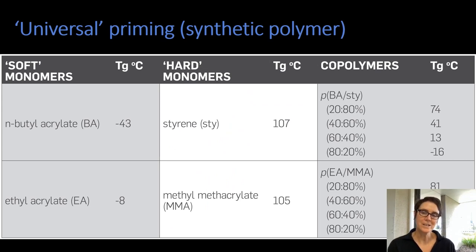Although characterization of the percentage combinations of monomers was beyond the scope of this study, it's useful to note that different monomers are combined to achieve desired acrylic product characteristics, such as softness and hardness. You can see here that combining a higher percentage styrene to butyl acrylate, for example, results in a polymer with a higher Tg, thus a harder polymer. We were surprised to find so many different formulations of copolymers, even within brands, and this indicates that there is a wide variety in the manufacturer in the coatings industry.